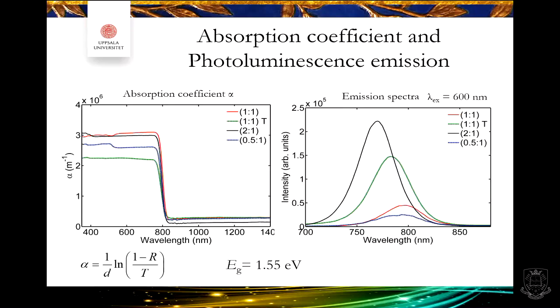So now from the transmittance and reflectance, I calculate the absorption coefficient. And here I have plotted the absorption coefficient instead. What is otherwise common in the perovskite is that you have a little bit of tail, not super much, but a little tail. This tail is usually localized states in the band gap, because otherwise, if you go from here, for instance, you measure long wavelengths, and then suddenly you have this high absorption. That is where the electrons are going from the valence band to the conduction band. Here is the band gap.